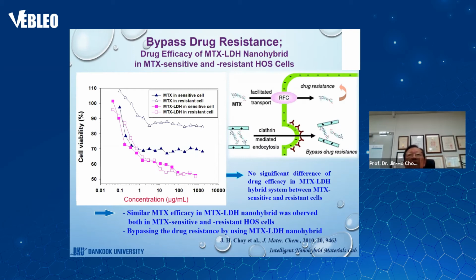We present here the first example of a drug-LDH nanohybrid system to overcome drug resistance. The MTX-LDH hybrid system can be highly effective in both MTX-sensitive HOS cells and the MTX-resistant HOS cells in terms of inhibition of cancer cell proliferation, cellular uptake, and intracellular retention. We also demonstrated that the uptake mechanism of MTX-LDH in HOS MTX-resistant cells was mediated by the clathrin-mediated endocytic pathway, the same entry as the LDH nanocarrier only. It is therefore concluded that the clathrin-coated pit for the internalization of MTX-LDH, which is completely different from that for free MTX, is responsible for accumulating high drug concentrations even in HOS MTX-resistant cells and bypassing the MTX resistance.